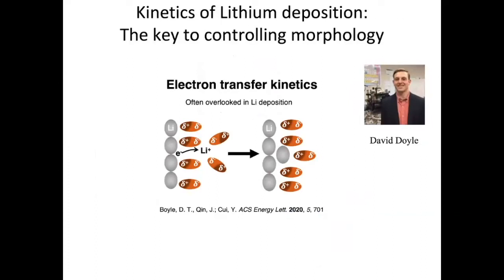Now I want to go deeper into the interface issue. We keep talking about the SEI, for example, for lithium metal, for silicon, for graphite. Can we really understand how the charge transfer is happening at the interface before the SEI forms? For example, right here, we have a lithium metal. You have a lithium ion solvated, in this schematic drawing, by the solvation shell. To deposit, the lithium ion needs to pick up an electron. The electron needs to transfer to the lithium ion, and it deposits or becomes atoms. Without the SEI, how does it look? The reason we are interested in this question is that this type of study allows us to really understand the lithium solvation shell and its impact on the charge transfer process free of SEI. Once SEI comes, another scenario will start to appear.